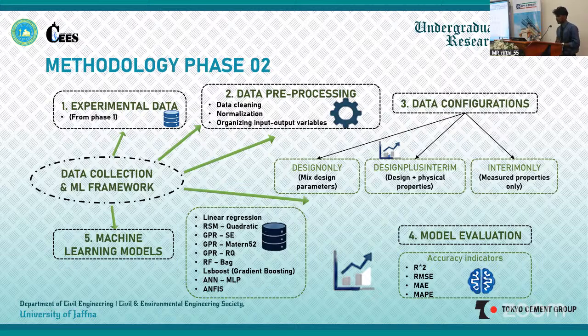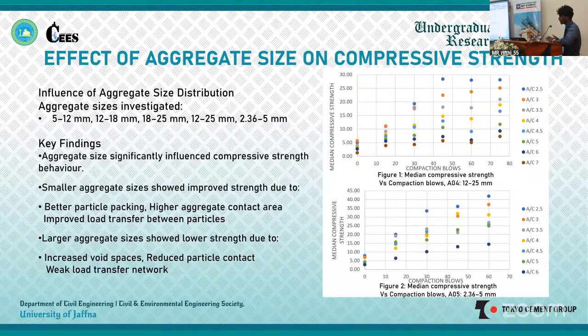This slide shows the effect of aggregate size on compressive strength, and this result shows how aggregate size impacts the compressive strength. Smaller aggregate sizes have a higher strength because the particles are packed together, and larger aggregates create more voids, so the concrete has a lower compressive strength. Also, increasing the compaction blows generally increases the compressive strength.